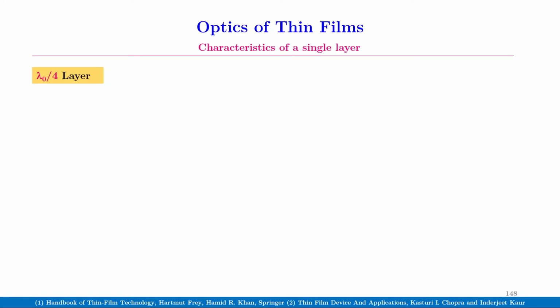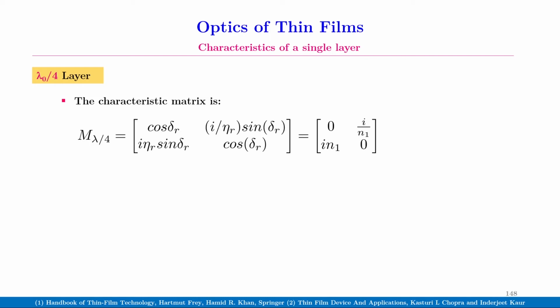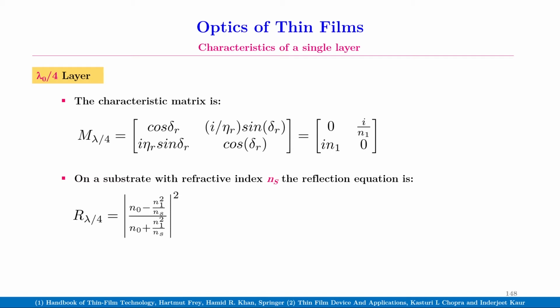We will now consider a layer of thin film which has a thickness of λ0 divided by 4. In that case, the characteristic matrix M(λ/4) equals the matrix [cos δr, i/η_r sin δr; i η_r sin δr, cos δr], which is equal to the matrix [0, i/n1; i n1, 0]. On a substrate with refractive index ns, the reflection equation is R(λ/4) equals modulus of (n0 − n1²/ns) divided by (n0 + n1²/ns), the whole square.